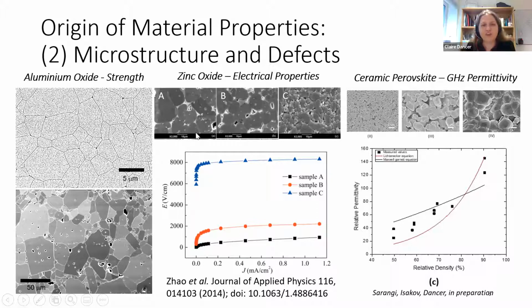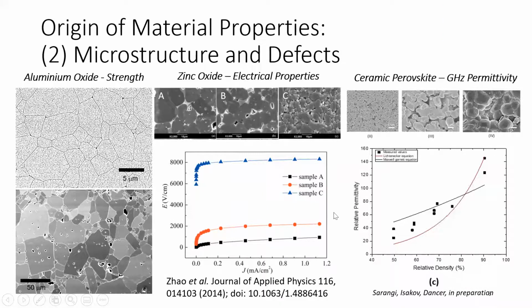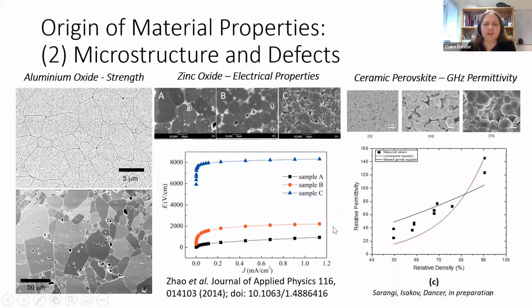And you can see from the SEM images that actually sample A and sample B are relatively similar. Sample C is quite a bit smaller in its microstructure. And when you come to measure the current voltage characteristic of these materials, you see that come through in the structure. So these are the same material. It's all zinc oxide, but they're showing quite different behaviors in terms of their electrical characteristics and properties. And this is where we get that degree of freedom of how we can control the properties of the material.